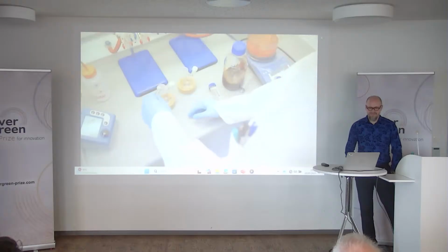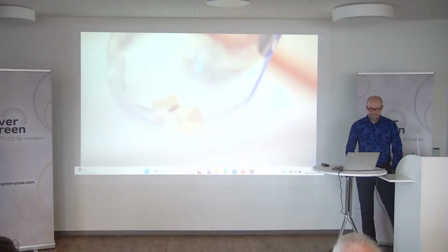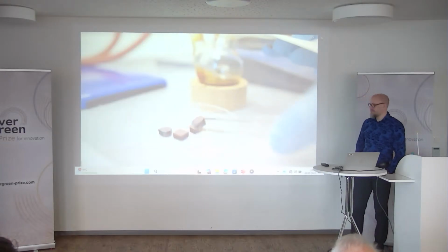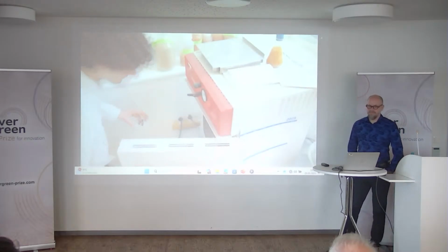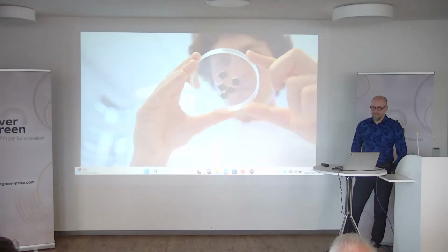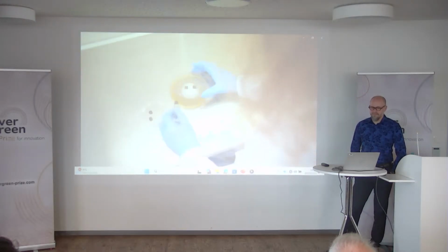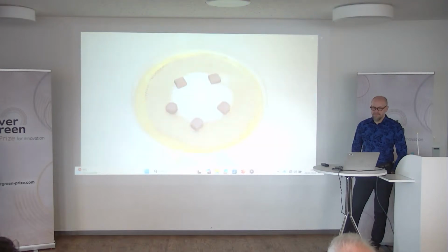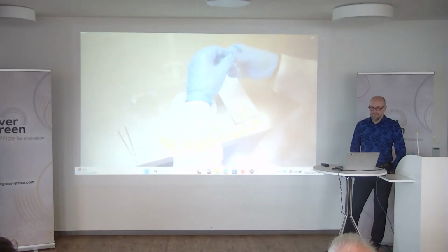Hyperlignification increases the wood mass by up to 90%. That's more than 10 times higher than previously achieved. The material shows greatly improved resistance to fungal decay and increased fire resistance.